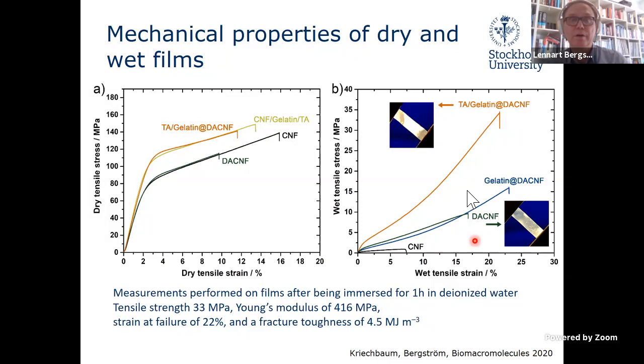The material has been immersed for 1 hour in deionized water, and then kept saturated during the tensile testing. The CNF is pretty useless here—it has a very low wet tensile strength and fails after about 7% elongation.